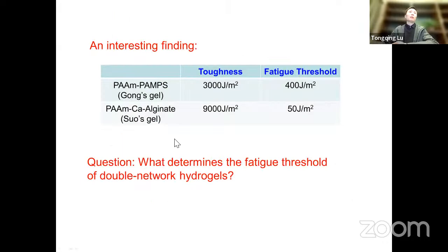But we think it's an interesting finding if we compare these two kinds of tough hydrogels. This is the first generation of tough hydrogel. We call it Gong gel. Its toughness is about 3,000, but its fatigue threshold is 400. And this kind of hydrogel, the toughness is larger, but the fatigue threshold is smaller. So now we have a question: what determines the fatigue threshold of the double network hydrogels?